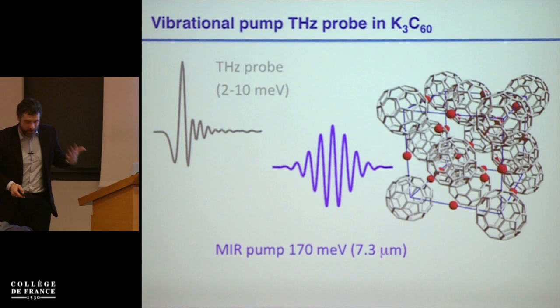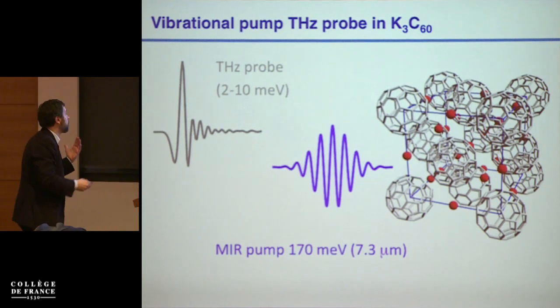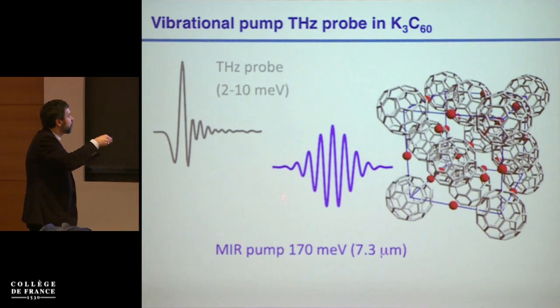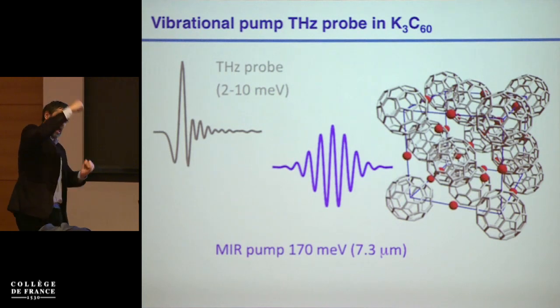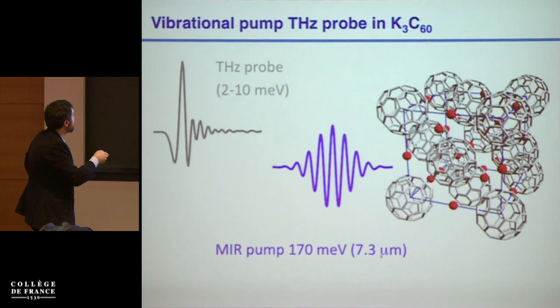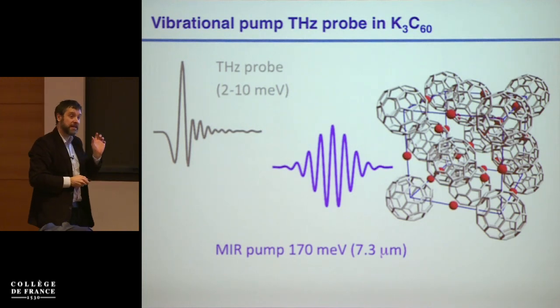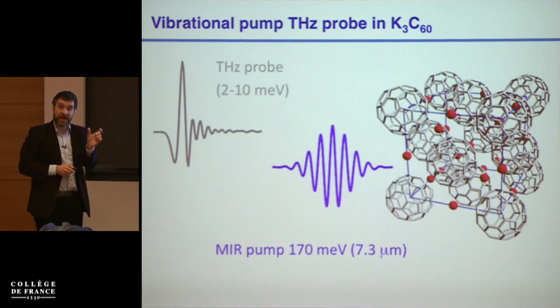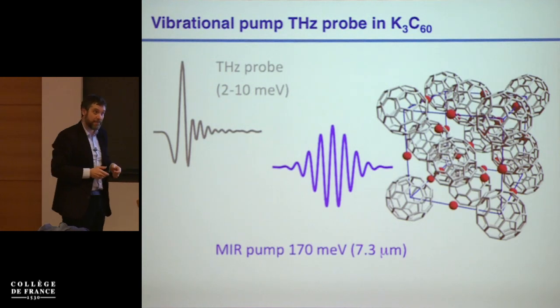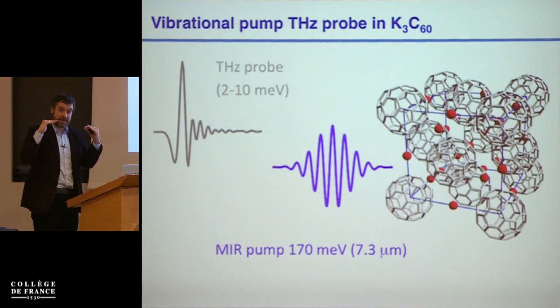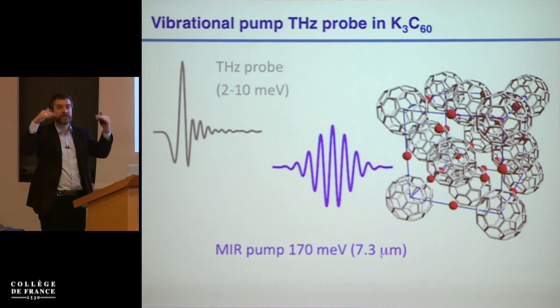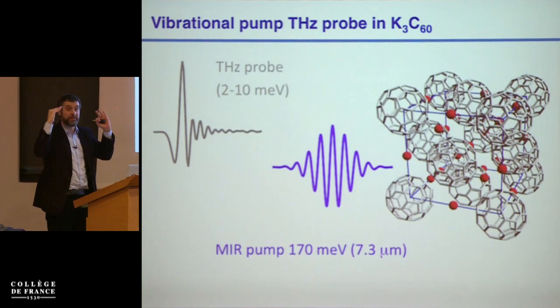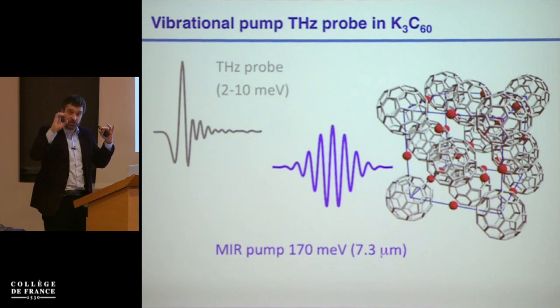So the experiment is the one that I've been telling you about for the last 2 hours, one in which we have a short mid-infrared pump that elongates these buckyballs along this direction. And then we have a second pulse that comes and probes the reflectivity in the gap region, which is where I observe a superconducting gap by cooling. And I start in the normal state at, say, 25 Kelvin or even 100 Kelvin. Remember the red curve. And I'm going to try to induce the blue state, which I could do only by cooling previously.